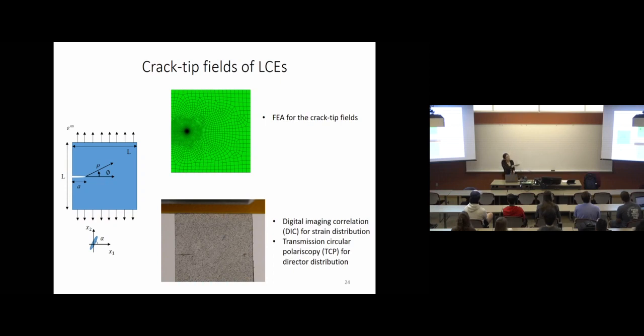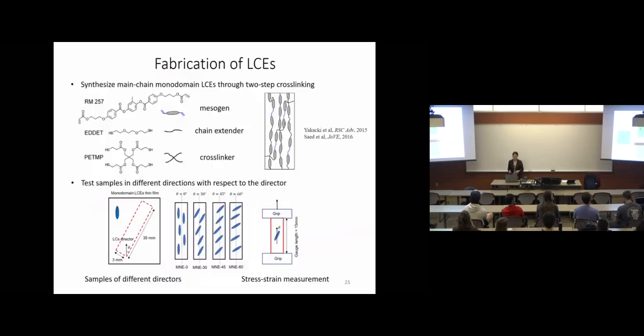So our methodology here is that we combine computation and experiments to study this. In particular, we use finite element to study the crack tip field, and we also use digital image correlation, DIC, to capture the whole strain field, and transmission circular polariscopy, TCP, to capture the director field. Let me first tell you a little bit more about our methodology before I move on to showing you the results of crack tip behavior.